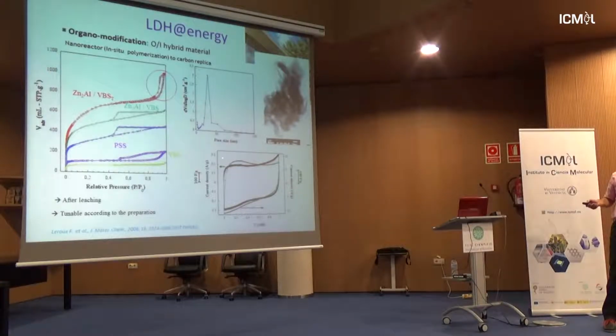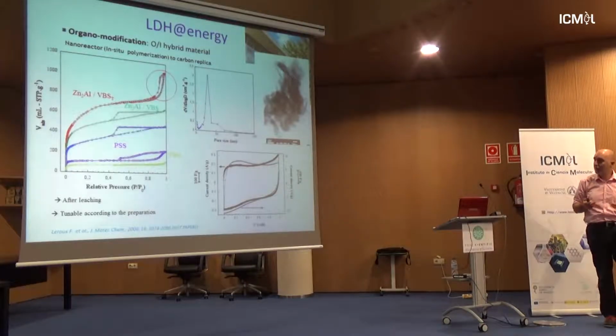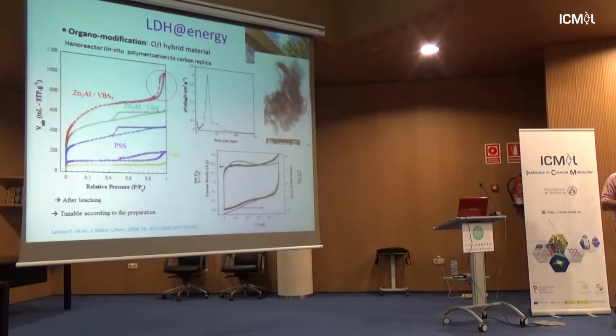So it's a system based on the capacitive behavior of electrochemical storage. It's not a lithium-ion battery, so it's not a Faradic behavior, but it's on the surface, so it's acting very rapidly, so it's a very powerful system. Not too much energy, but a large power efficiency. So it means it's very interesting for ignition or feedback in a very short period of time. If you need a large power in 1, 2, 10 seconds, you will need a supercapacitor. But for long-term energy demand, it will be more a lithium-ion battery or some other electrochemical storage with a large energy.